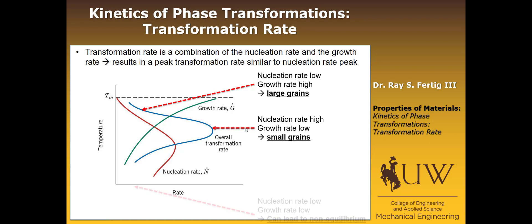If we cool it down enough such that the nucleation rate is low and the growth rate is low, then it can actually lead to non-equilibrium phases. And we're going to see this in the case of steel, which will be in the next lecture when we start talking about some of the phases that emerge as we develop microstructure during cooling in steels.